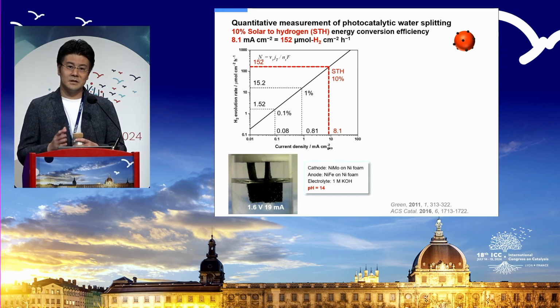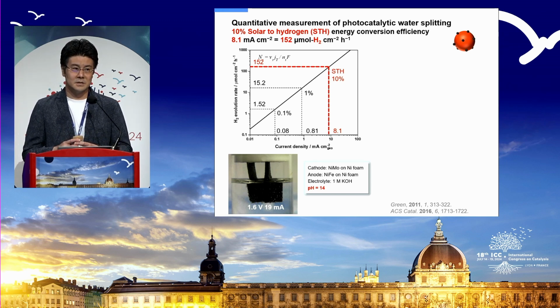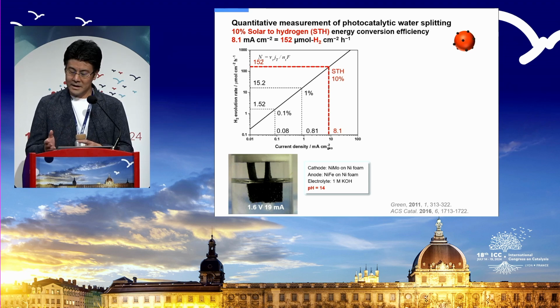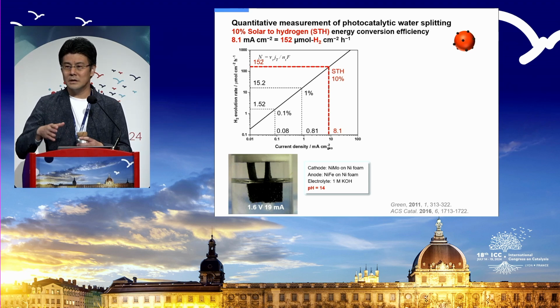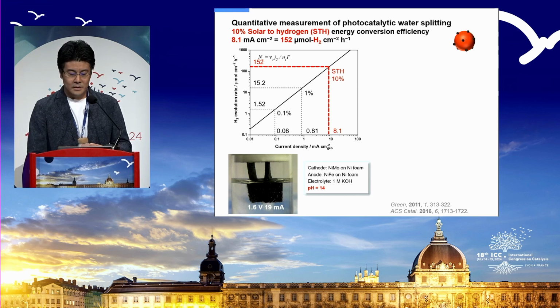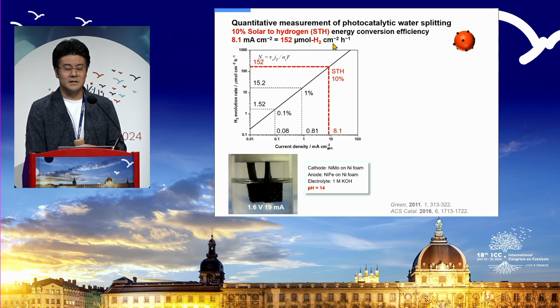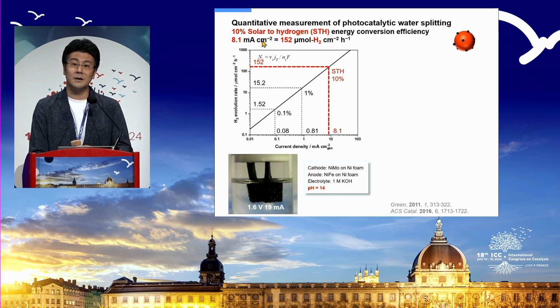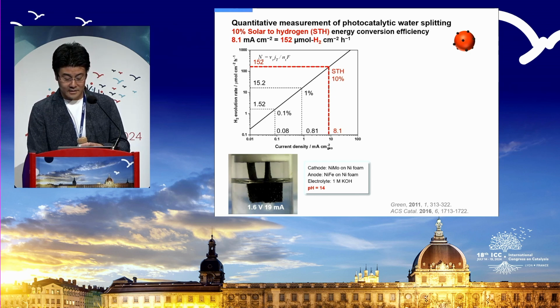We really want to achieve 10% solar-to-hydrogen efficiency. So we can translate the target production rate into current density. 10% solar-to-hydrogen efficiency means a hydrogen evolution rate of 150-ish micromole per square centimeter per hour. That corresponds to about 8 milliamp per square centimeter, to do actually an electrolyzer.